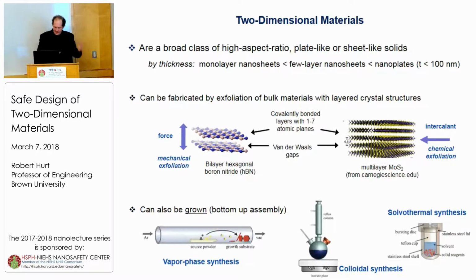As we see here, here's hexagonal boron nitride on the left, which is a true single atom thick monolayer material. There it's shown as a bilayer structure. And on the right is molybdenum disulfide, in which the individual monolayers themselves consist of covalently bonded atoms with 3 atomic layers, sulfur, molybdenum, sulfur, separated by these van der Waals gaps. And you can mechanically exfoliate these layered materials using shear forces to rip them apart into nanosheets, or you can chemically exfoliate them, typically by inserting a chemical agent in between the layers, decomposing that agent, producing gas, and creating pressure that blows apart these structures into nanosheets.